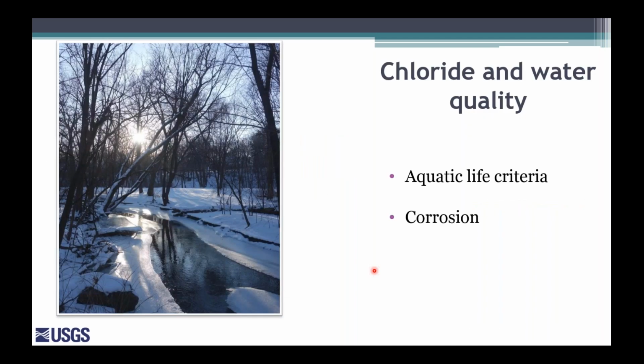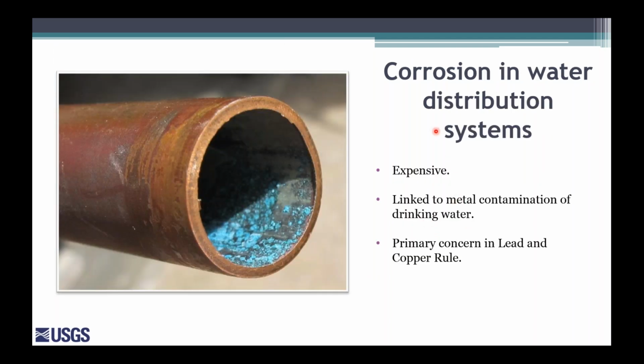So if we think about the linkages between chloride concentration and water quality, two main issues really stand out. And the first is that elevated chloride concentrations have adverse effects on aquatic organisms. Chronic toxicity occurs at 230 milligrams per liter of chloride, and this level can actually be exceeded for periods of time in urban streams in snow-dominated areas. And as I mentioned before, elevated chloride concentration can also promote the corrosion of water infrastructure. And as we talked about earlier, corrosion is a ubiquitous problem for water infrastructure. It's been estimated to cost $36 billion annually nationwide. Corrosion in water distribution systems is also known to be important for human health, as we mentioned earlier, and metal contamination of drinking water can occur due to corrosion.